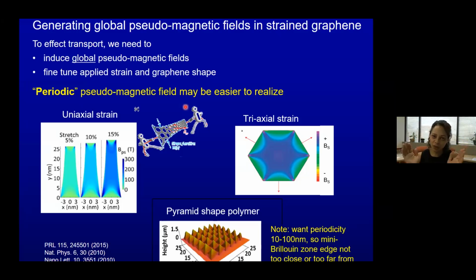But in order to see that at an accessible energy scale, something less than applying 100 volts to the sample, you have to have a periodicity of the scale of 10 to 100 nanometers, right? If the periodicity is too small, then these extra dips and extra features you see are too close to the Dirac point and can't be distinguishable. And if the features are too big, then the additional dips come at too high an energy scale. So in order to see the features in transport due to pseudomagnetic fields, we want to have periodicities on the scale of 10 to 100 nanometers. Okay, and you'll see us focus on this pretty soon.